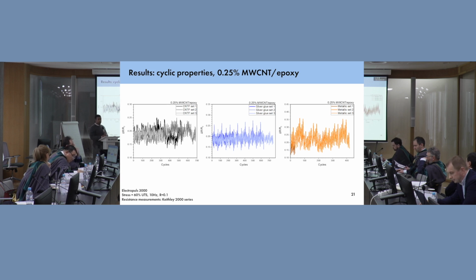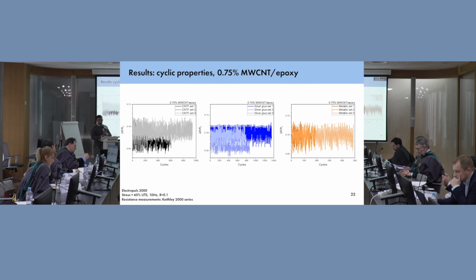So our carbon nanotube fibers, as we can see, delta R is in the expected range of what we see for tensile. We see a good response. We see cycles generally between, in this case, 5 to 700. For our surface applied, we see somewhat in the same range, but for our metallic ones, we start to see that failure slightly sooner. When we move to a higher weight percentage, this also becomes a bit visible here for the multi-wall carbon nanotube composites.